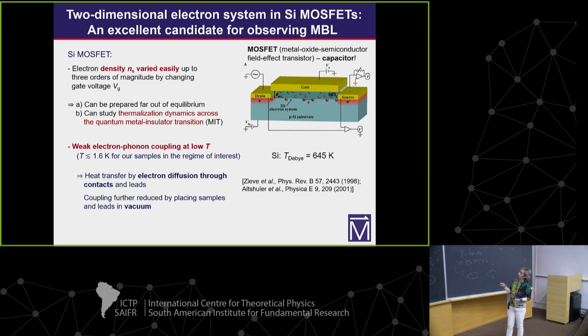So there are no phonons, and the heat transfer from the 2D layer to the rest of the world is by electron diffusion through these contacts, source and drain, and then you have leads that go up to room temperature because this is all in a cryostat. So you can reduce this coupling to the environment further by placing the samples and leads in vacuum. And this is what we have done, unless I tell you otherwise.